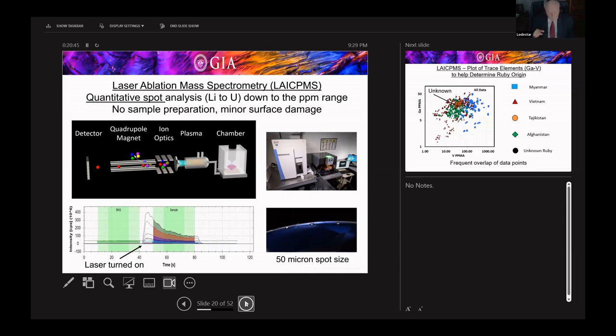The graph on the bottom left is what the operator is looking at when he has the instrument running. Time is on the bottom axis. From about 10 to 40 seconds, you're going to be collecting a background signal. The laser's not on. When the background is done, you turn the laser on at about 45 seconds, and you see all the graphs jump up. You let that burn through the outer surface of the material for a moment, and then you've got about 30 seconds of data collection.